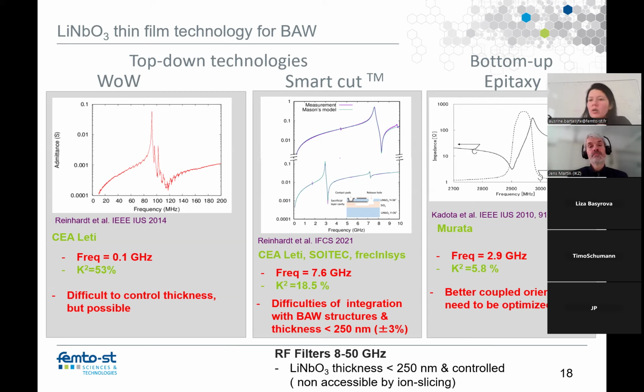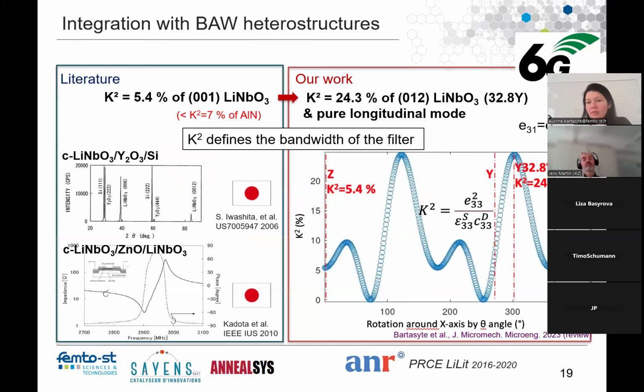And before our group worked on grown films, there was work from Kadota, from Murata, who showed in 2010 that it's possible to grow C-axis oriented films on an electrode. And they attained a frequency of 2.9 gigahertz with a coupling of 5.8%. But this C-axis orientation has the same or even slightly lower electromechanical coupling than aluminum nitride. It was not possible to compete with aluminum nitride at that time. We just simply do a sputtering.